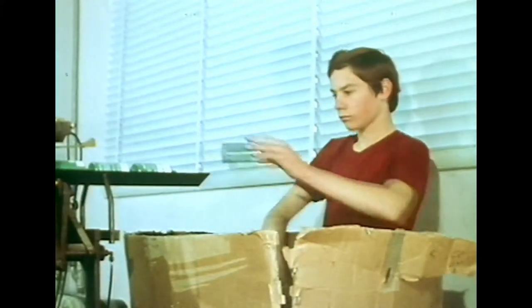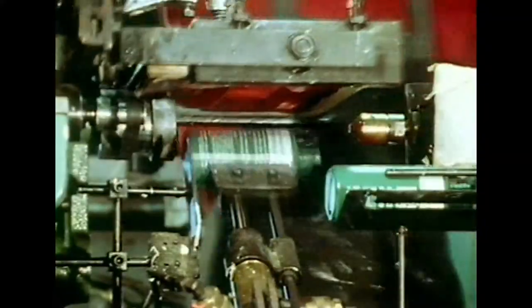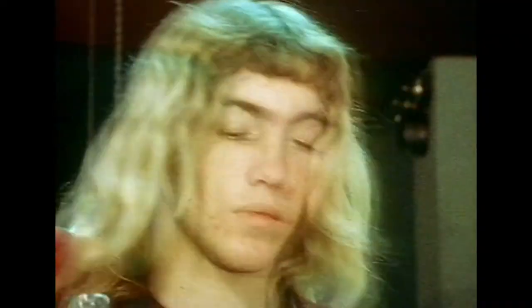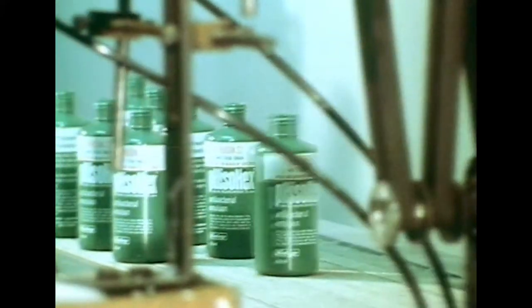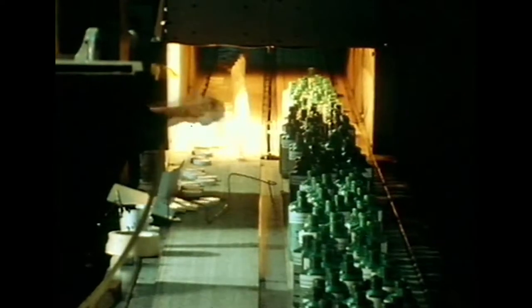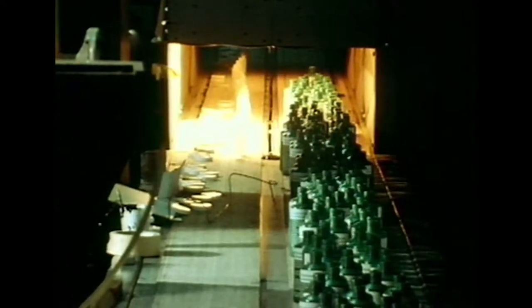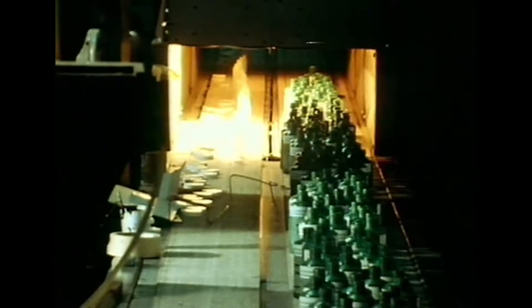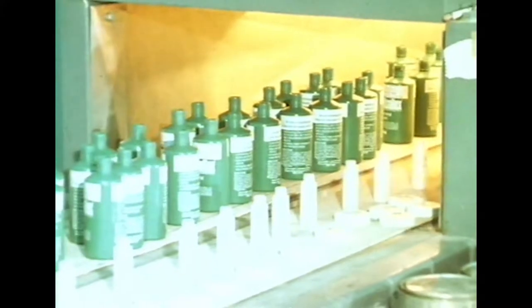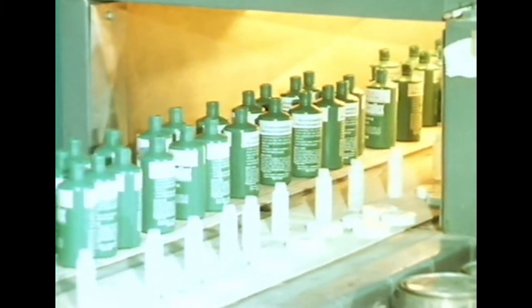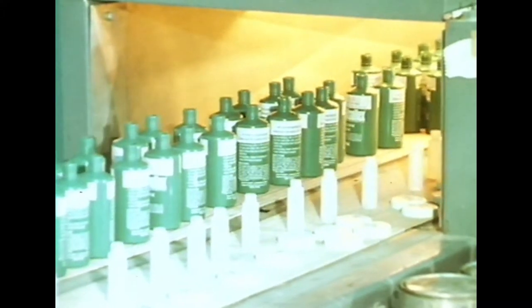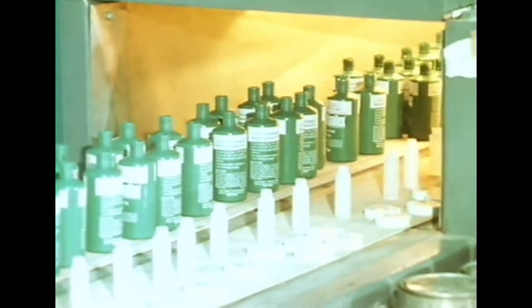At Ace Screen Printers, the greatest production barrier to the screen printing of thousands of plastic bottles per day was the space required for air drying of the product. Bottle and container labels are applied by the screen printing process. Twin variable speed belts pass through a double oven, each side fitted with high-powered tubular lamps. The radiant density is controlled so precisely that the printing inks are dried in a little more than a minute, while the low melting point plastic bottles are unaffected. The system completely eliminates the space and labor problems associated with air drying.